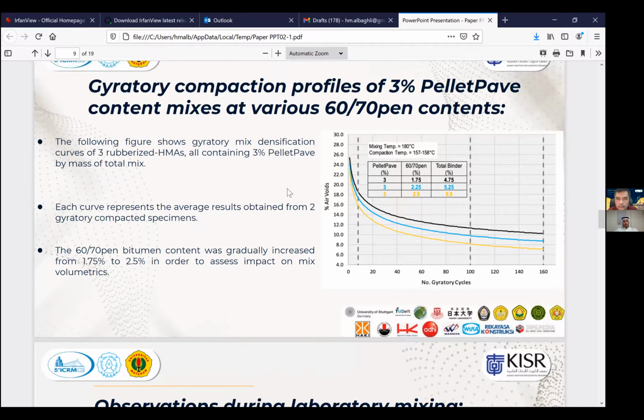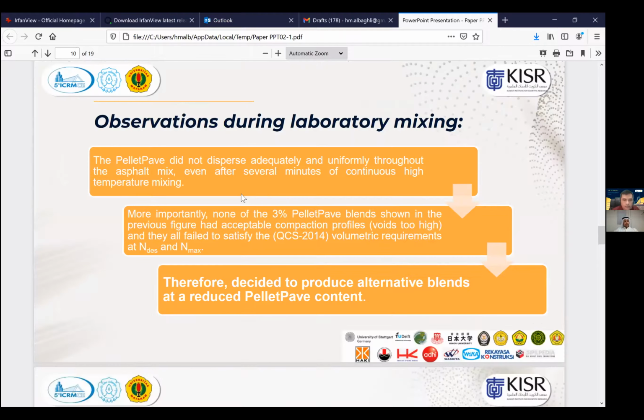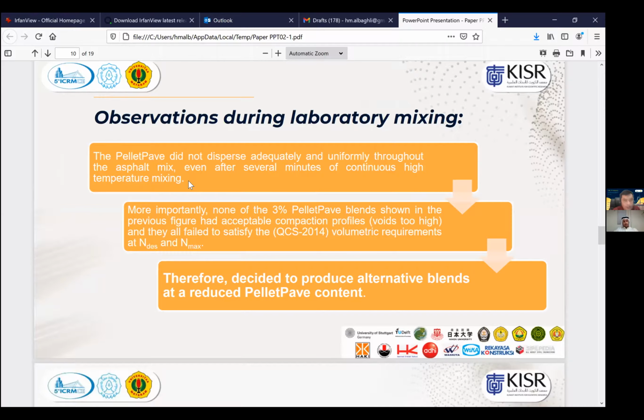they failed to satisfy the newly adopted Kuwaiti specifications. Also, during the mixing in the laboratory, we had some challenges where the Pellet Pave did not disperse adequately and uniformly throughout the asphalt mix, even after several minutes of continuous high temperature mixing. So therefore, we decided to produce alternative blends at reduced Pellet Pave content.